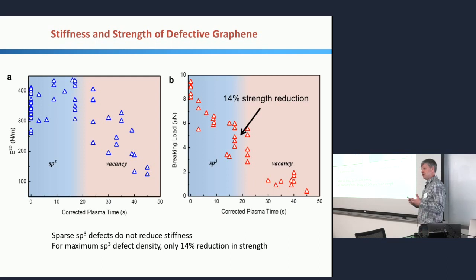Again, that's as to be expected. Small point defects shouldn't change the overall stress-strain behavior of the material, which is dominated by the bulk of the material. But then once we start putting holes in the material, there's less stuff. Every time you have one of these holes, the material will be more flexible around that hole, and we see the Young's modulus start to go down. On the other hand, if you look at the breaking load, it starts to decrease as soon as we add even these sp3 defects. And again, that's because breaking strength is a function of the weakest point, not the bulk of the material.